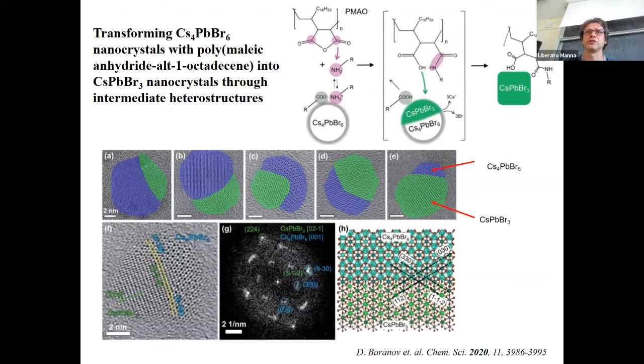You can do this transformation of cesium 4 lead bromide 6 into the perovskite also in a more careful way. For example, you can take a polyanhydride polymer, and what happens in this case is that the anhydride group will react with the ligands on the surface of the nanocrystals and also with some of the free amines present in the solution of the nanocrystals. They will strip completely the ligands and also acidify the medium. And these conditions lead to the extraction of bromide ions and of cesium ions, which are complexed by the polymer. And you have this transformation into the 3D phase.